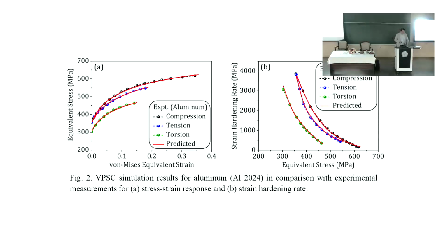Now we look into some simulation results. These are the same cases we saw before for fitting, where we did empirical fitting without thinking, no physics, just a function, mathematics, fitting with computer, fast and surprisingly efficient because it describes the experimental curve very well. Now we are doing physics, simulation work with the VPSC model, and the result is compared again with experiment. It is actually almost as good as the empirical one. Very small deviations, perhaps you can discover here, they are not covering exactly each other, the curves, while the empirical one was.